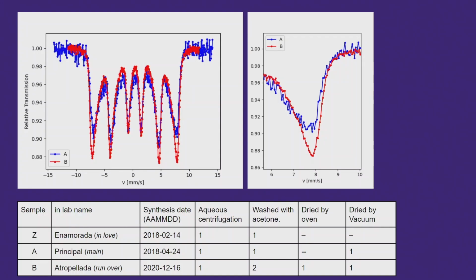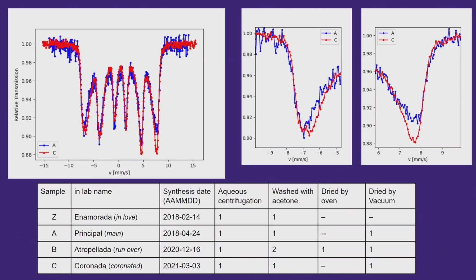So in Argentine it's: match, rematch, and well, tiebreaker. We made a third synthesis, and the result was not equal to the first and not equal to the second one. Here something different appeared. We have again the same situation, but on the other side, we have the presence of two peaks. It's more like magnetite than maghemite, which was the first one.